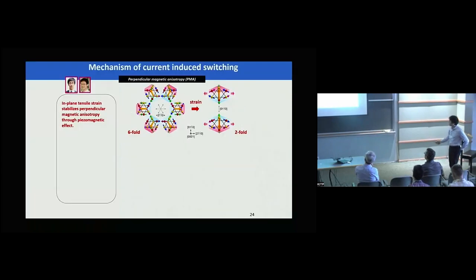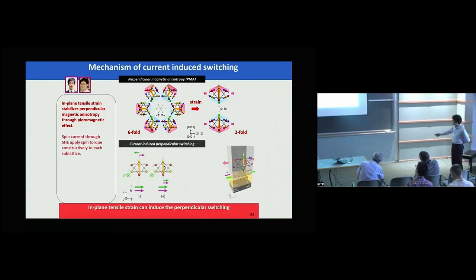Okay, so here comes some of the mechanism. As I said, strain is important for us to align the domain. In this case, there is a tensile stress in the plane, meaning there is a compressive stress. This is the Poisson ratio, and that actually stabilizes twofold symmetry perpendicular to the direction of this substrate, and spin current through the spin Hall effect applies spin torque constructively to each sublattice. So this is consistent with what we have discussed for the field theory argument.